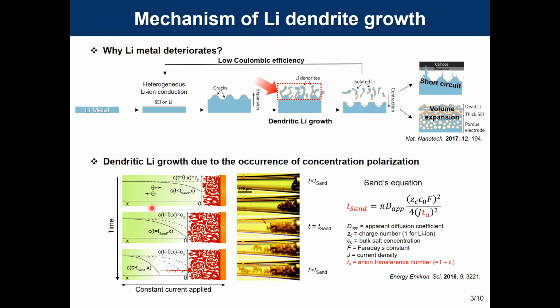Here you can see during the charge process, lithium ions migrate from the electrolyte to the lithium metal anode. Then the concentration of lithium ions at the electrode-electrolyte interface reaches zero, which is called Sand's time. In order to alleviate concentration polarization, decreasing the anion transference number is required for suppressing dendrite formation.